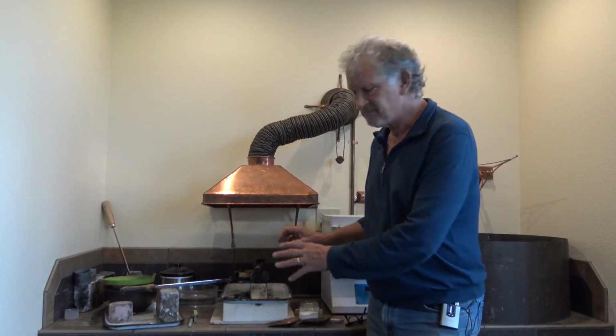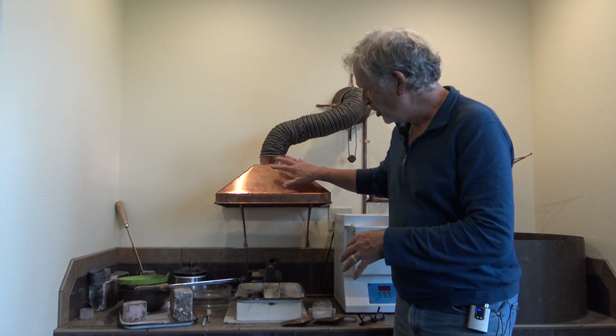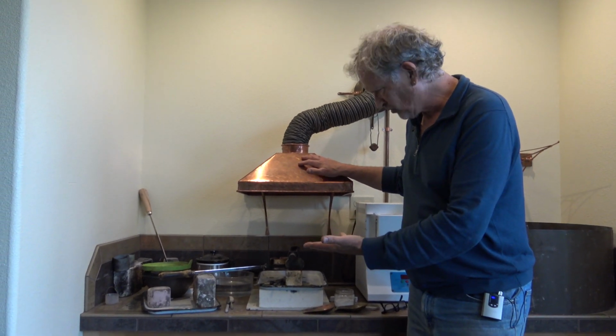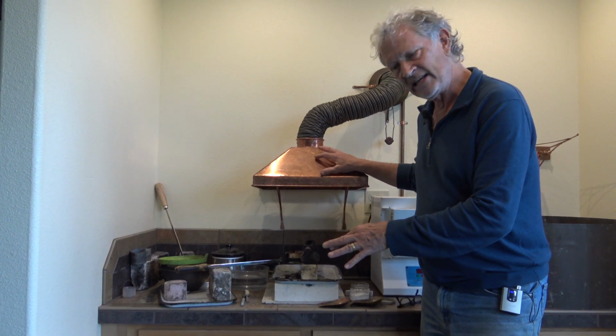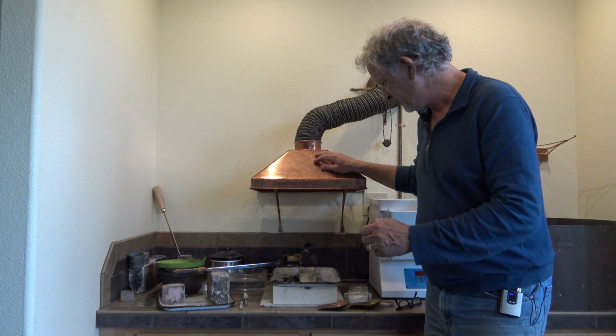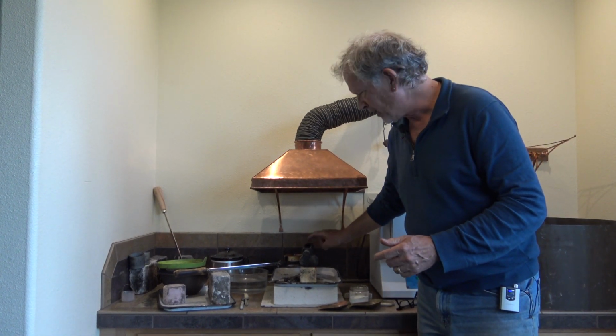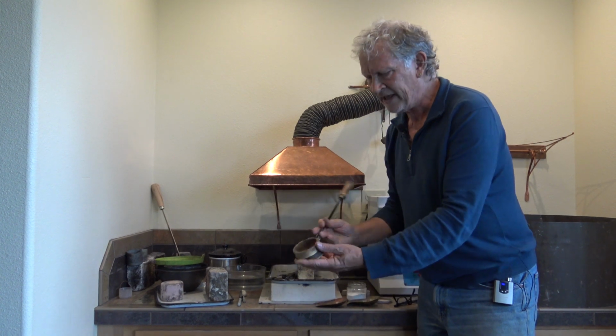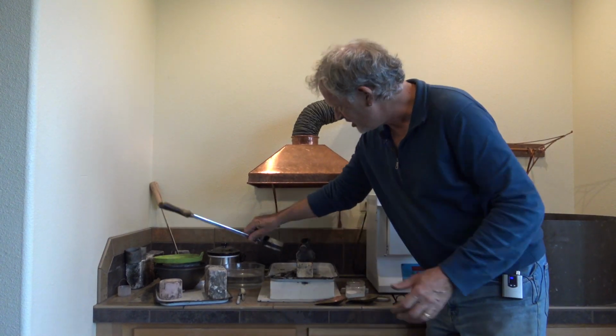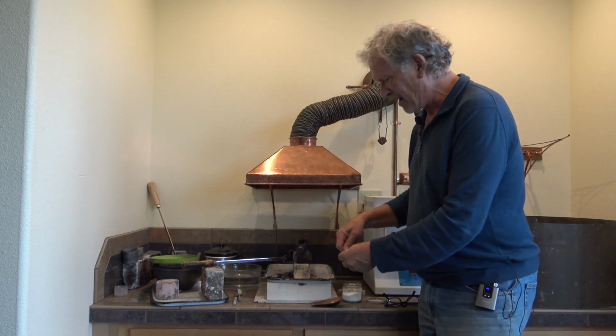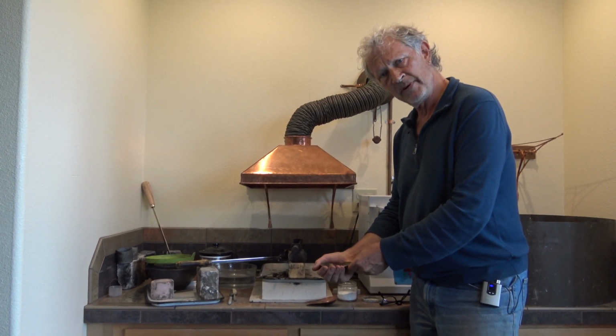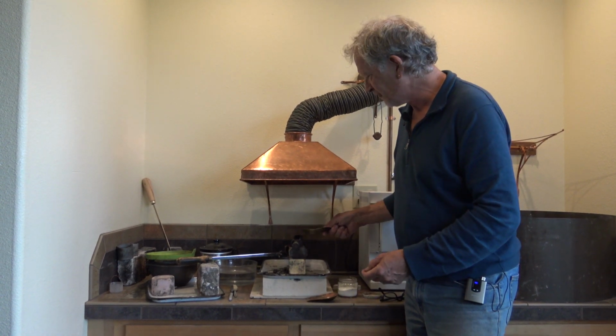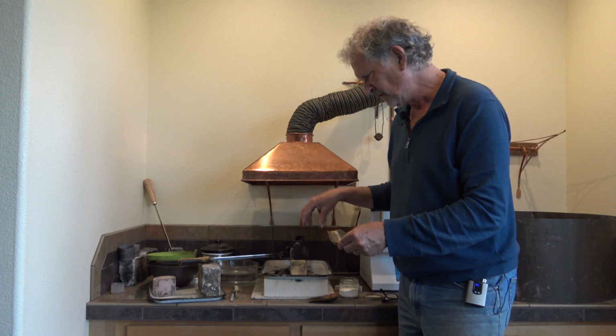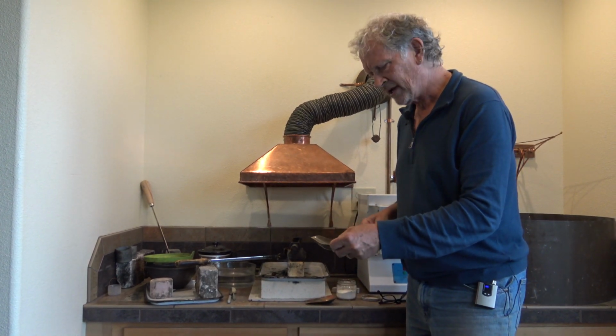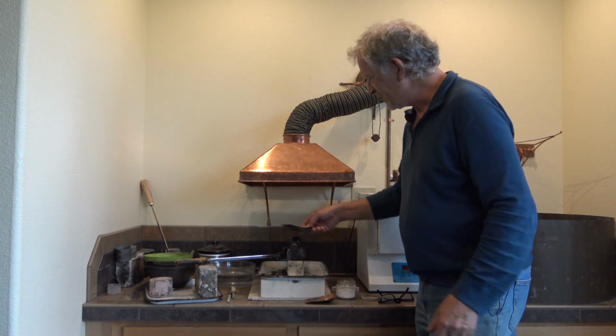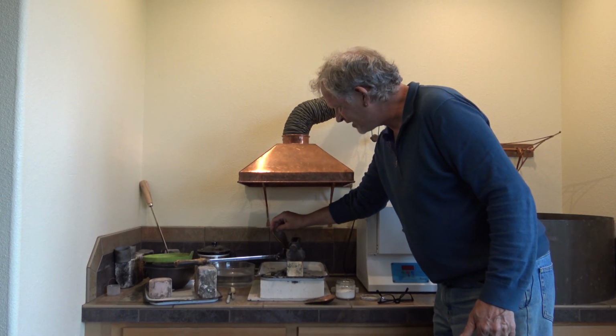Okay, so this is my alloying and melting area. I have a hood here for evacuating the gases from the torch and the melting procedure, which is a really good idea because it does put off a good bit of toxic fumes. I have an ingot mold ready here for pouring, and I have a 5-ounce crucible on a handle that I use for pouring. What I do is I take some scrap metal of the same alloy that I'm going to be melting the filings of, and I put that in the crucible first and melt it down, and then I add the filings to the puddle. And we'll be doing this close up, but I just want to give you a quick overview of what's going to happen. So I'm going to put these scrap into my crucible, and I'm saving the filings for after I've started the melt.